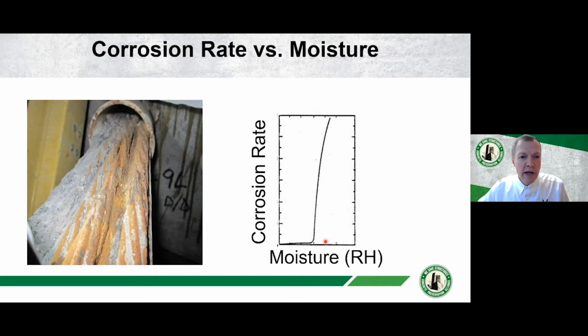If the strands are in grout, the grout is going to create an alkaline environment around the steel. That alkaline environment is going to protect the steel from corrosion, and it doesn't matter whether it's wet or dry, the strands will be protected. If there's voids in the grouting for whatever reason, or if you're dealing with unbonded post-tension tendons that don't have any grout at all, then the corrosion rate of the tendons in the voided sections, or the corrosion rate of the unbonded tendons, is going to behave like this, and is going to be very dependent on the moisture content that they are exposed to.